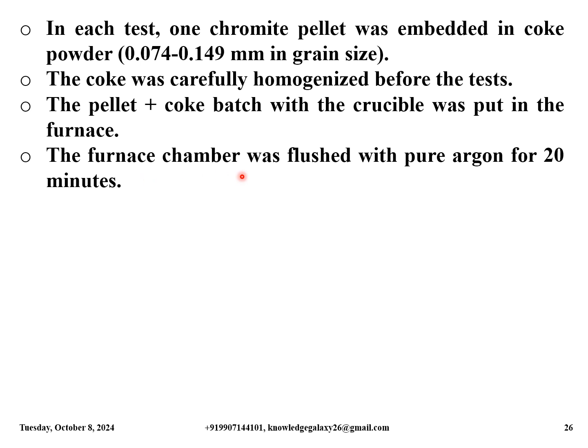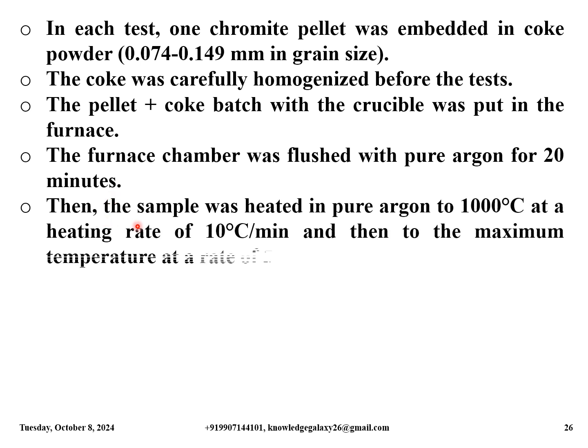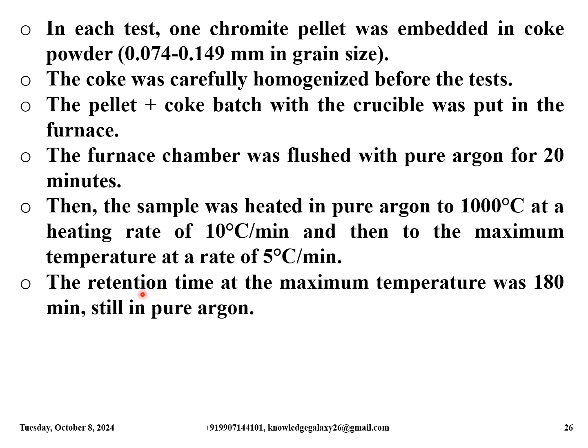The furnace chamber was flushed with pure argon for 20 minutes. Then the sample was heated in pure argon to 1000 degrees Celsius at a heating rate of 10 degrees Celsius per minute, and then to the maximum temperature at a rate of 5 degrees Celsius per minute. The retention time at the maximum temperature was 180 minutes, still in pure argon.